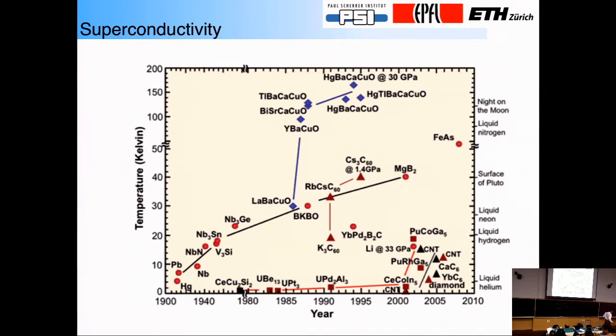Of course, the thing that generates the most popular excitement in solid-state physics is shown here. So this is superconductivity as a function of time. Actually, it ends in 2010. Since 2010, there's been one important development, which is that we found a fairly conventional hydride, which has a TC under pressure of about 200 Kelvin. So over the last 100 years, since the discovery of superconductivity by Kamerlingh Onnes in mercury, down at a few Kelvin, we've seen essentially what amounts to 2 orders of magnitude increase in the transition temperature.